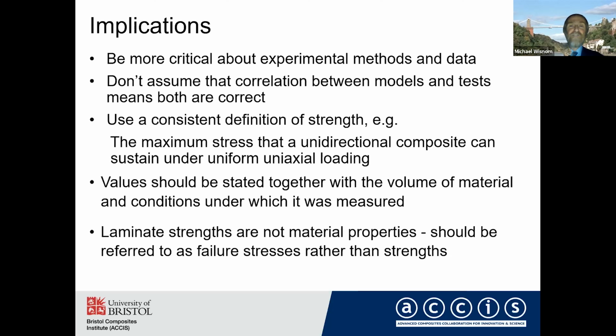I think we should use a consistent definition of strength, and the suggestion here is we use the maximum stress that a unidirectional composite can sustain under uniform uniaxial loading. When we do report values, we should state the conditions under which they were measured and the volume of material. And we should recognize that laminate strengths are not material properties, and I would prefer to refer to those as failure stresses rather than strengths. Might seem a fairly subtle distinction, but I would prefer to keep strength to the ultimate material parameter and use failure stresses for cases where we have so-called strengths which actually depend on the configuration.